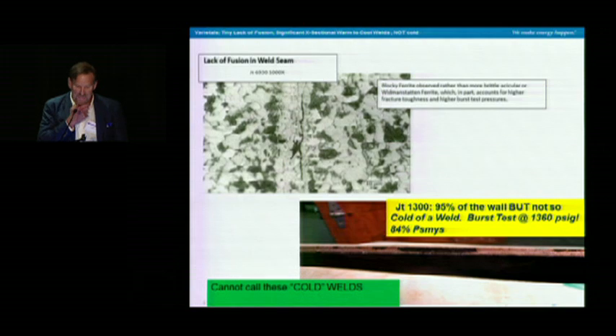So this next one down here, and we'll show a little more about 69, you'll see that joint 6930 and see what the burst test was, but if you look down there below that joint 1300, it doesn't take a rocket scientist to look at that one and say that black stuff looks like it's nearly through wall. We talked about through wall, leak versus rupture, stable versus unstable on the API 579 FAD.